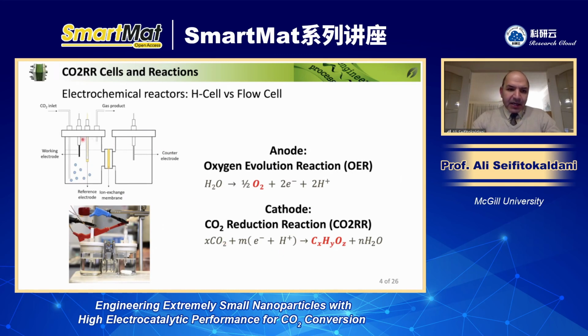So in the H-cell, as you may notice here, we have a solution, which is our electrolyte, to provide the ionic conductive media. And then we apply the electrical circuit outside. Then the CO2 needs to be purged inside the electrolyte, and you see here a real picture of our setup. So the CO2 is purged inside the electrolyte, and then we will have a saturated electrolyte. Then the CO2 needs to diffuse from the bulk of the solution to the surface of the electrode where the reaction is happening. So at the working electrode, we have the reaction ongoing. And there are some limitations associated with that.